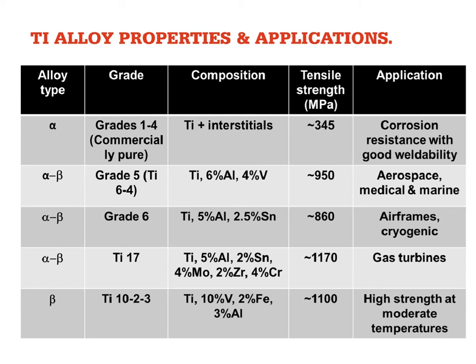Another category of non-ferrous alloys are the titanium alloys, and there are a wide range of those, many of which are heat treatable, because I mentioned briefly that iron has a transition at 910 degrees C, the basic fundamental crystal structure. Well, titanium does something similar at 883 degrees C. So we can use that to our advantage by adding different alloying elements and creating what we call alpha or beta alloys. You can see here some of the chemical compositions: titanium plus additions of aluminium and vanadium. This one, so-called 6,4 or titanium grade 5, accounts for about 75% of all titanium alloys. It's very much the workhorse because it has an alpha and beta structure, and that's used for a very wide range of applications.